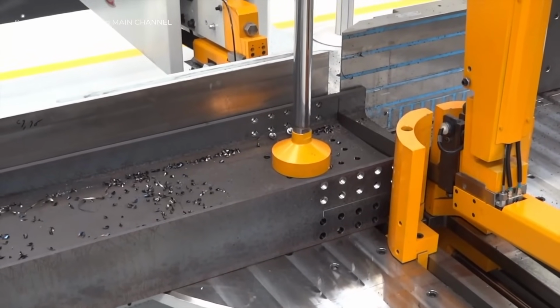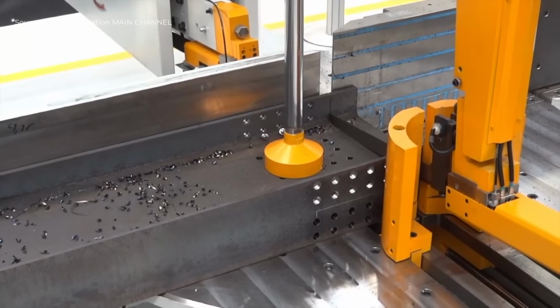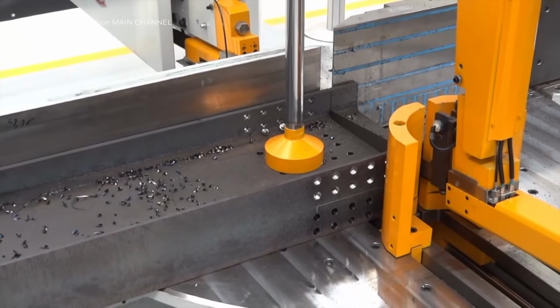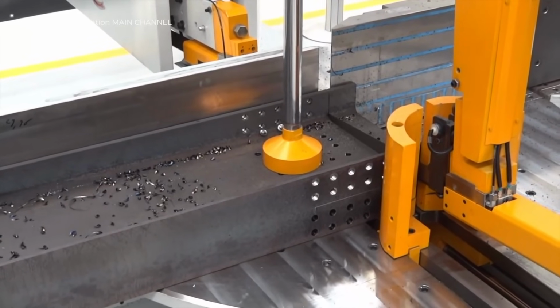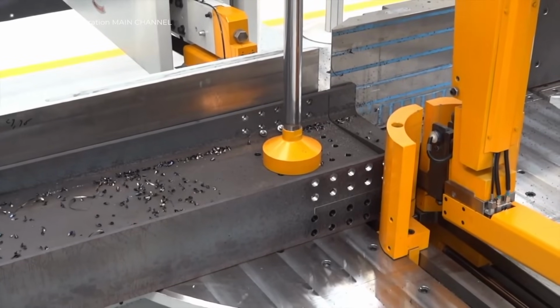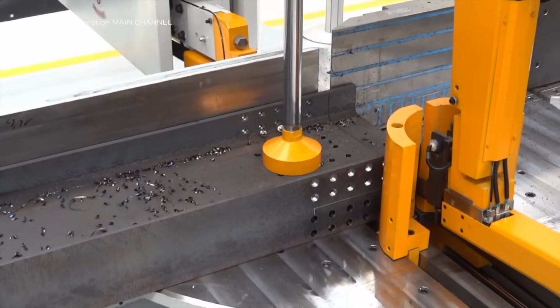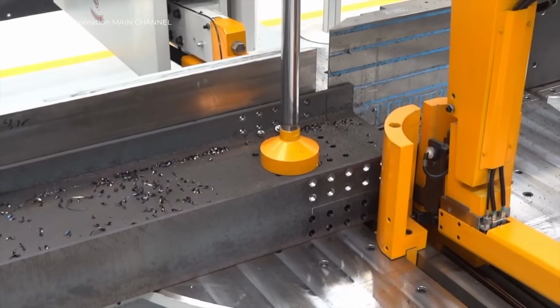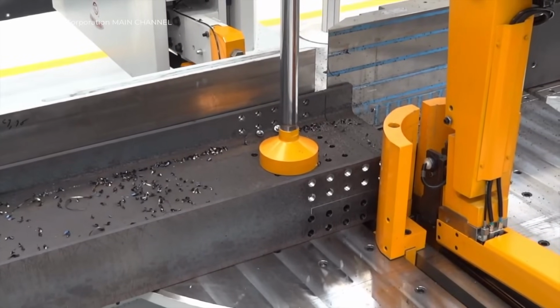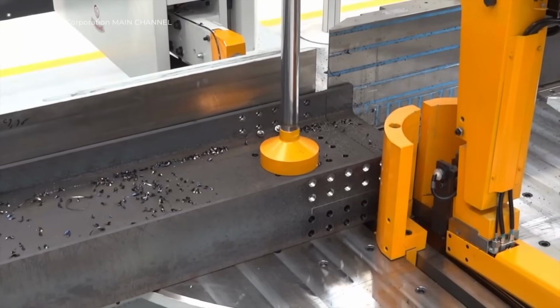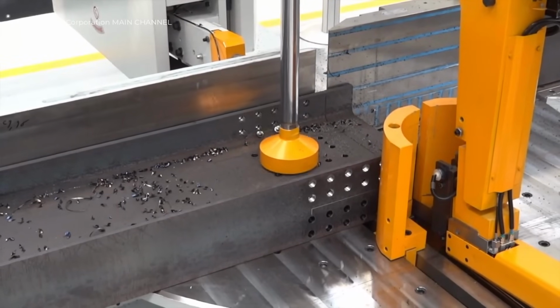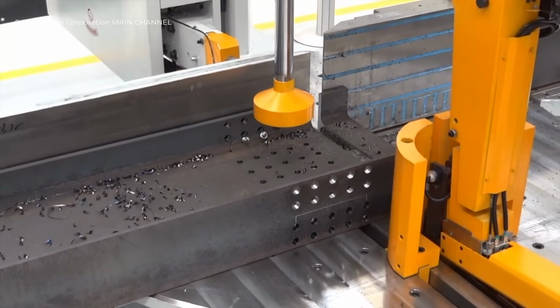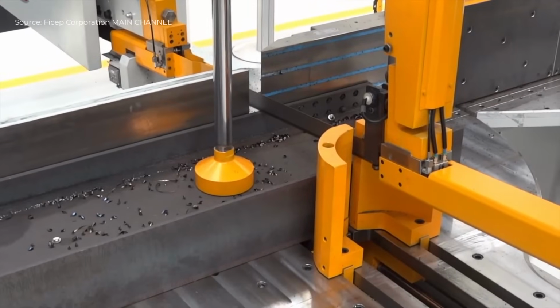Each flange receives 20 holes with a 20 mm diameter, while the web is drilled with 20 holes of 18 mm diameter. The holes are offset by 5 mm between the flanges and the web. Thanks to the sub-spindle positioning, all 60 offset holes are drilled in just 76 seconds. This rapid operation is made possible because each spindle operates independently, maintaining maximum productivity and precision without repositioning the beam.